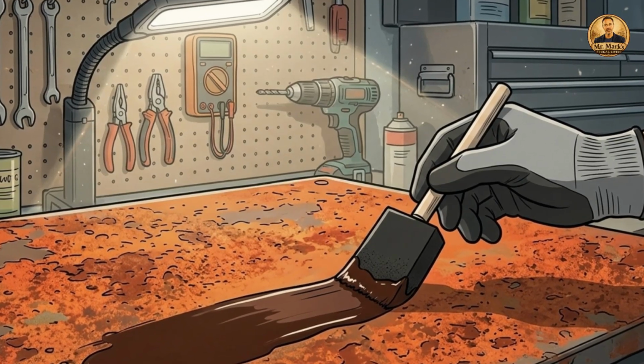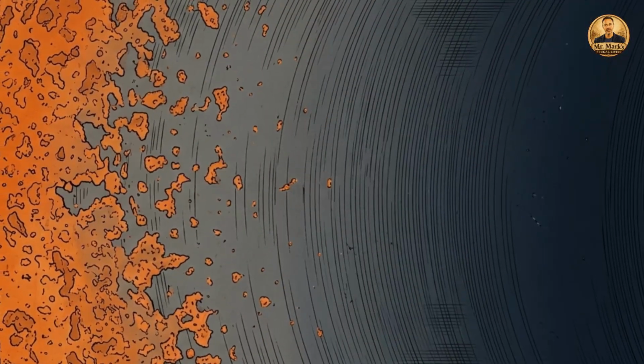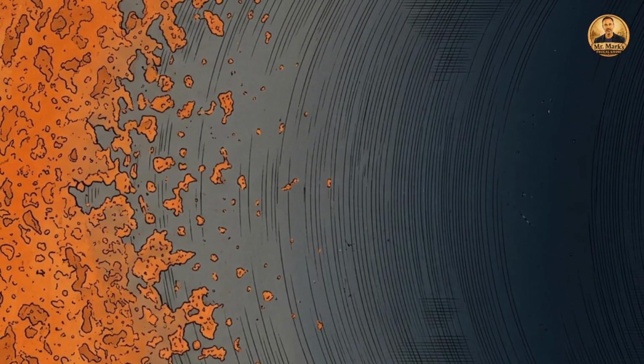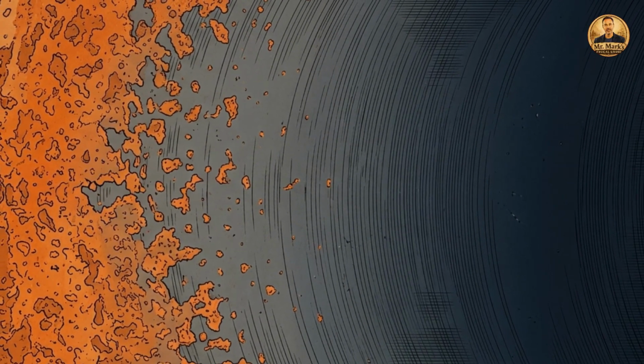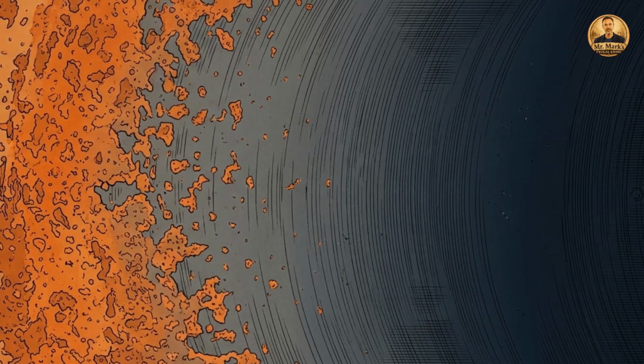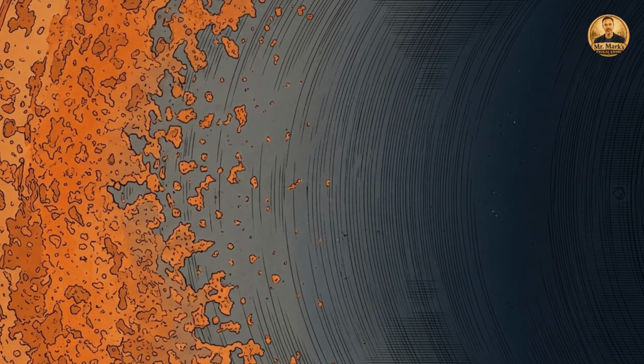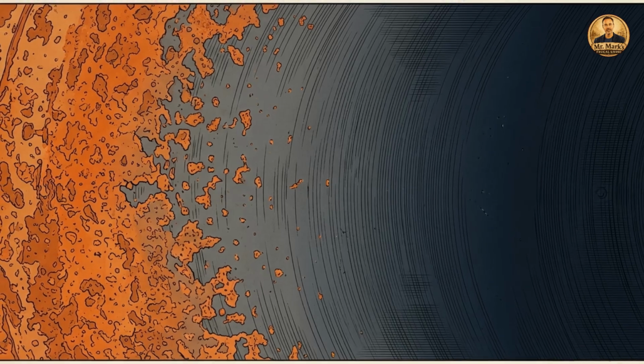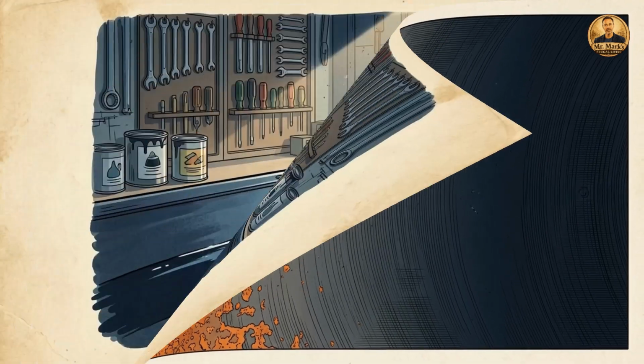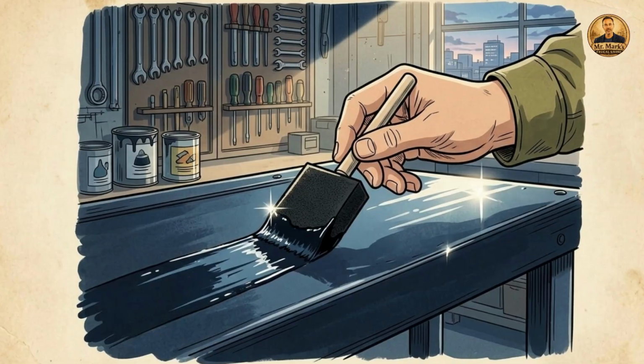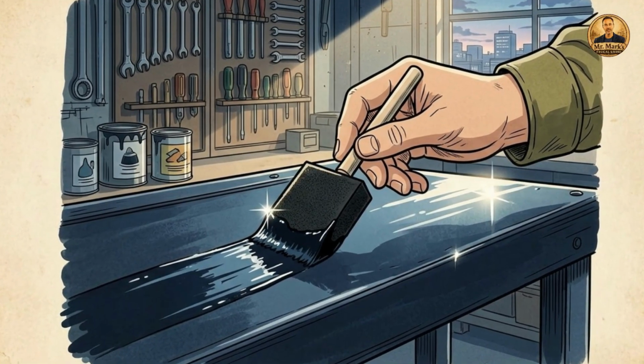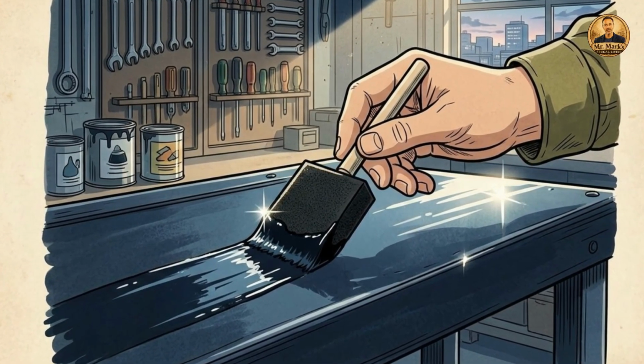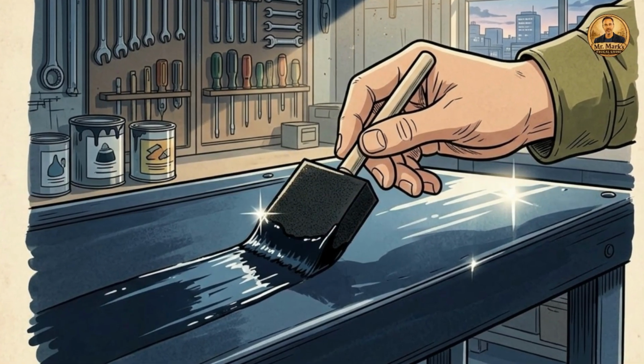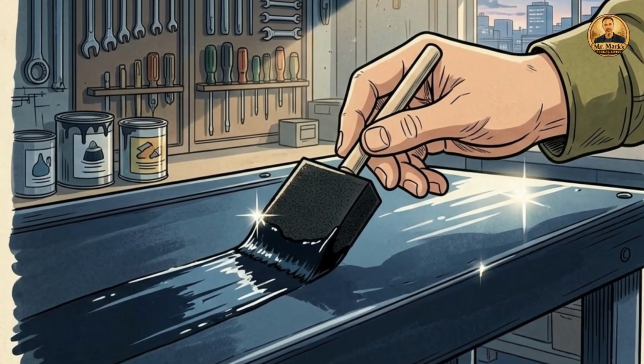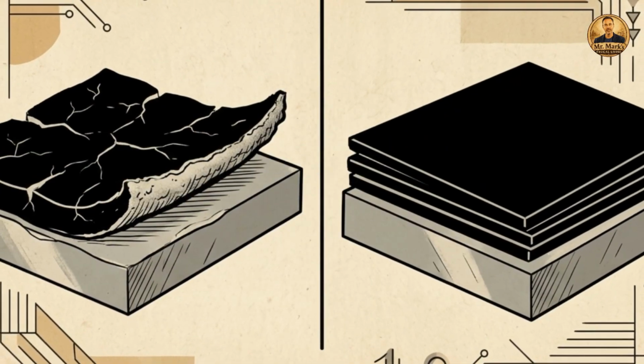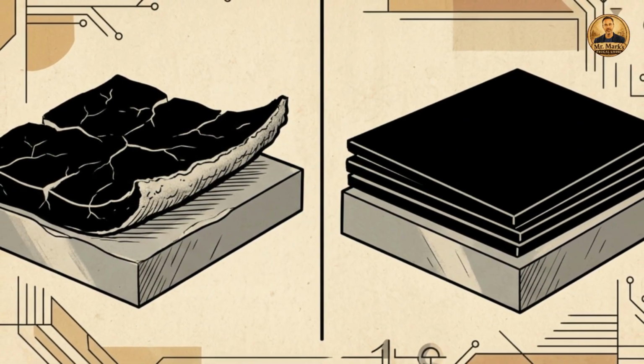Brush the solution evenly across the surface. Within 10 to 15 minutes, you will see the color shift, orange to dark, gray to blue-black. That is ferric tannate, forming in real time, right in front of you. Let it dry completely, 2 to 4 hours, depending on temperature and humidity. Then, apply a second coat. The Canadian Conservation Institute specifically recommends multiple thin coats with complete drying between applications rather than one heavy coat. Excess ferric tannate that is not fully reacted can flake.